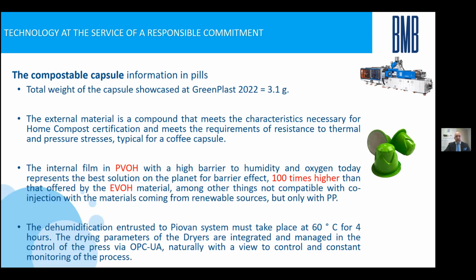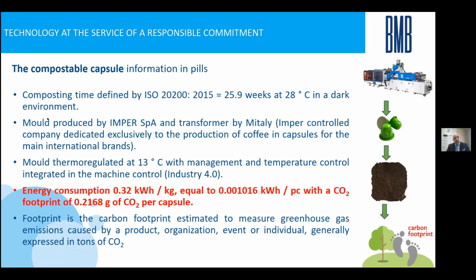Of course, the machine is able to connect all by OPC-UA. In red, you can see one important information. Energy consumption is 0.32 kilowatt-hour per kilo. That corresponds to, you can see, only 0.001016 kilowatt-hour per piece, with emission of CO2 footprint only of 0.2168 grams of CO2.